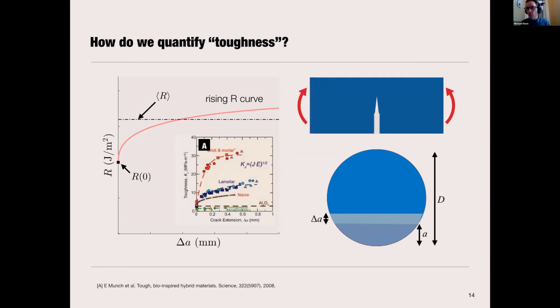The fracture initiation toughness should be a material parameter. It should be a constant, or roughly so, though not necessarily the case in heterogeneous materials. And the average value of R is not. This corresponds to work of fracture. It can be shown that average R is actually twice the work of fracture. And that can be size dependent on the material. It can be sample geometry and loading configuration dependent. So we need to be careful when we're making comparisons with this.